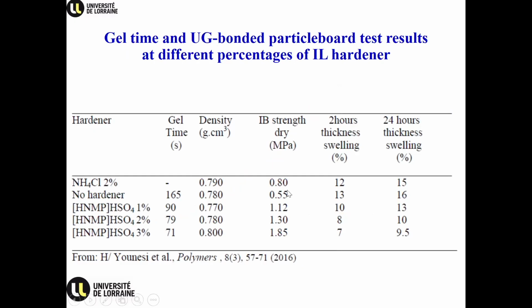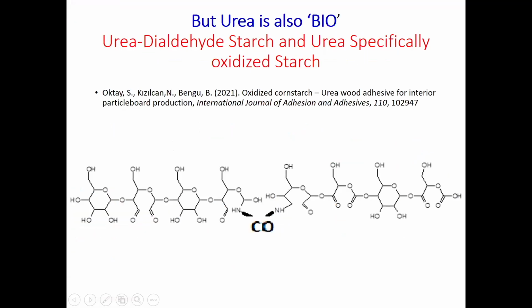I show you some particle board test results, for instance, with ammonium chloride, 2%, with no hardener. And when you use 1, 2, or 3% of ionic liquid, the dry internal bond test value you get is much higher. At 2%, you get 1.30, when with ammonium chloride, you will have 0.80 with a good urea formaldehyde resin. Urea is also bio.